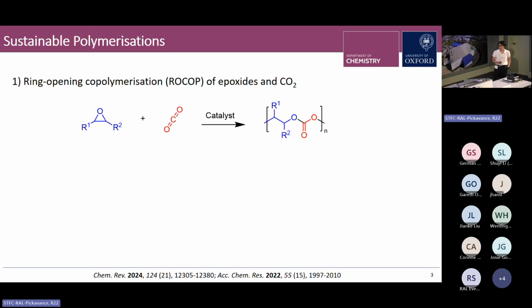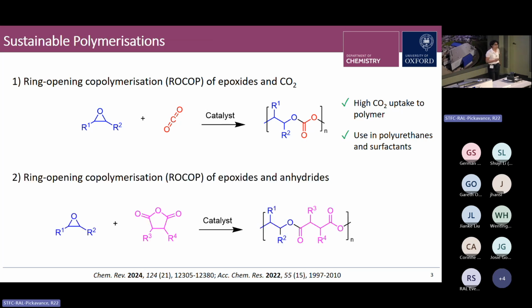So one of the methods we look at to do this is via the ring opening copolymerisation of epoxides and CO2 as a method of generating aliphatic polycarbonates. And this reaction is gaining significant interest because it allows for high CO2 incorporation into the polymer, and also the polycarbonate product finds applications in the synthesis of polyurethanes and also in CO2 derived surfactants. I'll also be looking at the related ring opening copolymerisation of epoxides and anhydrides as a well-controlled route to polyesters, with applications in packaging and clothing, for example.